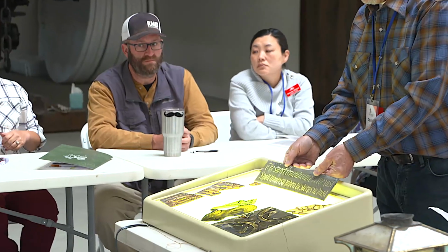So these are real common uses of flash glass, and that's nameplates. So these are broken nameplates that have come out of old windows that I've reproduced. But this is a purple flashed glass that's been acid etched, and they etched through the purple down to the clear, and then black tracing was painted around the edge of each letter, and then a gray mat across the face of the piece, and then it's fired in the kiln.